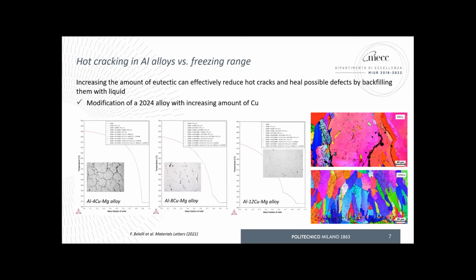Of course, it was a very important question you put on the table. Here we were considering only the possible strategy to remove the hot cracking phenomenon. And then it goes with it that at the same time, you should also preserve the available strength, or in general the target properties to be achieved. So here, we were not considering for the moment the evolution of the mechanical strength. I can presume that it might be lower than the original one, which was the silicon-free alloy, but again, it's a kind of compromise or trade-off we have to consider for the right design.